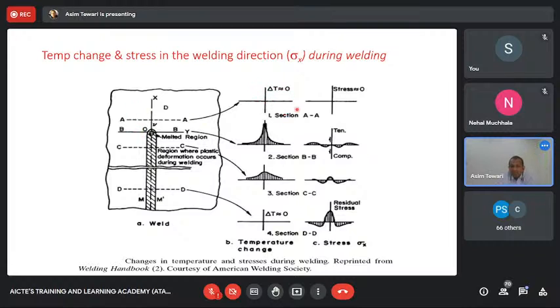So there is no stress and no delta T. Delta T is also equal to 0. Once you start coming close to it, what happens? The delta T starts increasing and you are at a BB section. So in this section, you are having the center expand more than the rest. And thus you start having very high stress in the center, and those center stresses have to be compensated by stresses of the opposite side on the sides. So you essentially have a compressive stress in the center and a tensile on the sides. And this is how it becomes.